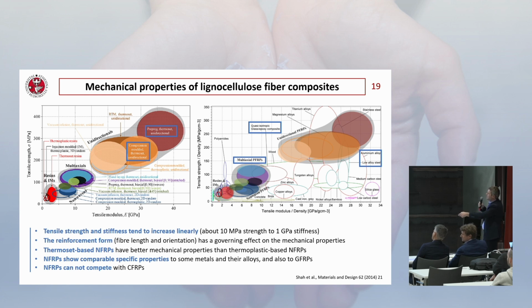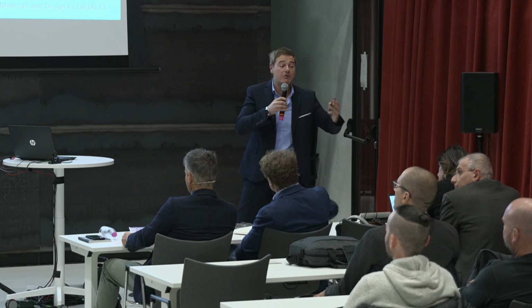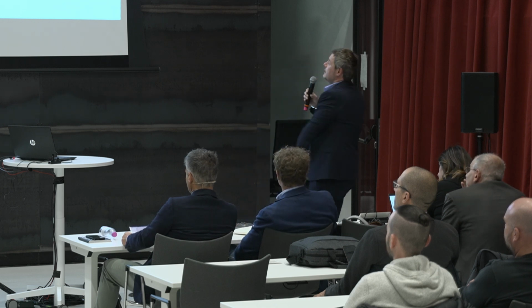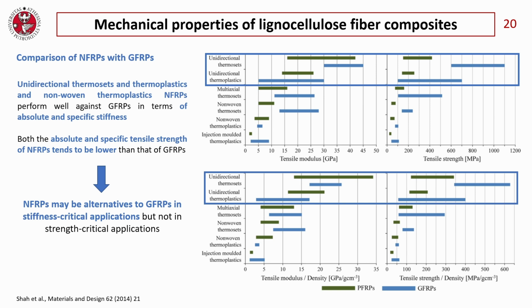Obviously, the reinforcement form has a governing effect on the mechanical properties, in the sense that the unidirectional composites perform better with respect to the bidirectional or non-woven fabric composites. Thermosetting-based materials are better in general with respect to thermoplastic. And these kinds of composites have comparable specific properties with respect to glass fiber reinforced polymer and some metals and their alloys. Once again, these kinds of composites cannot compete with the carbon fiber reinforced polymers. So the competitor is glass fiber reinforced polymers.